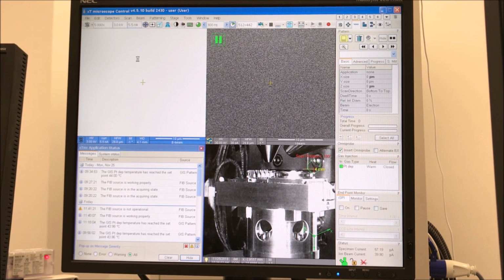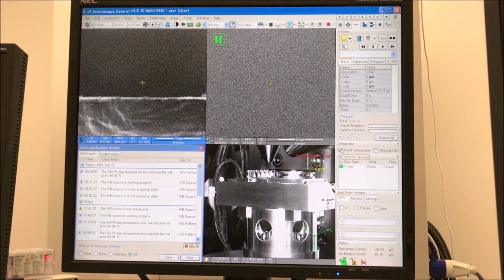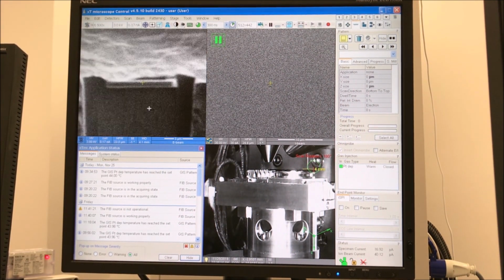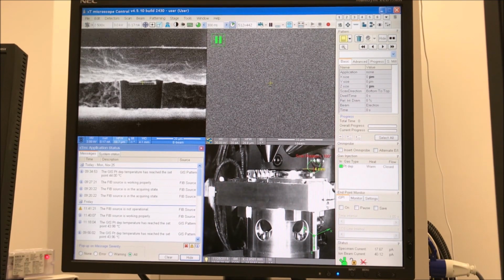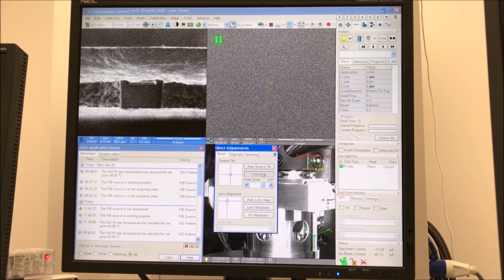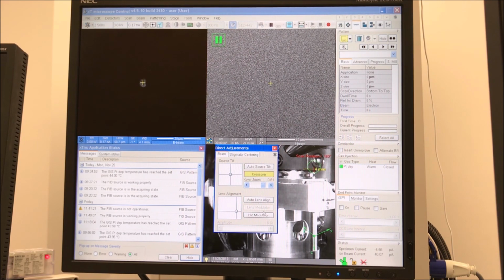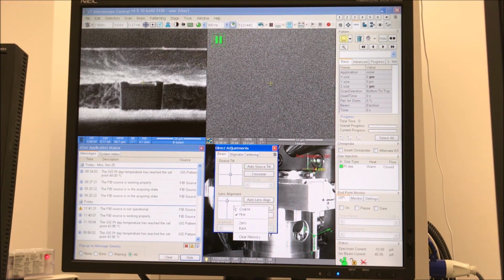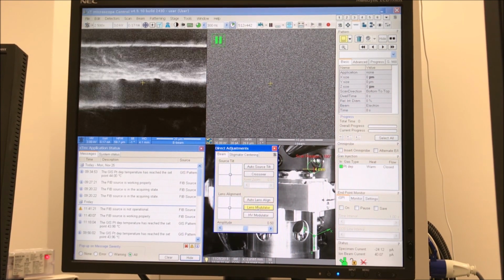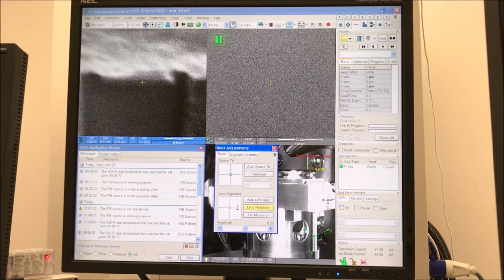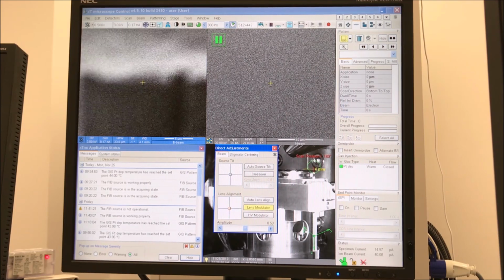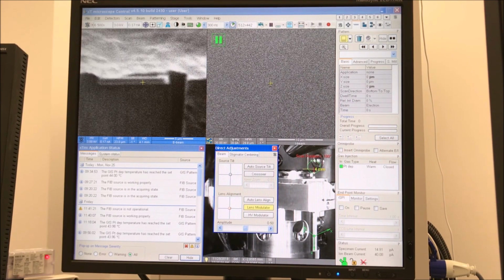And so when you're electron beam imaging while final thinning, you want to use a much lower electron beam current. I reduced it from 5.5 nanoamps to 0.17 nanoamps. And the reason you want to do that is you're going to get less contamination buildup on your sample by using a lower electron beam current than you would with a higher one, and you obviously don't want contamination on your lamella when you're TEM imaging it.